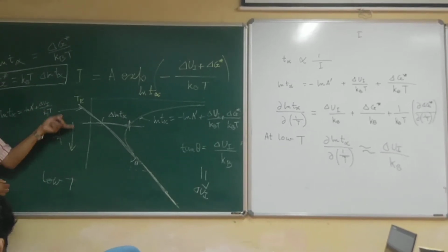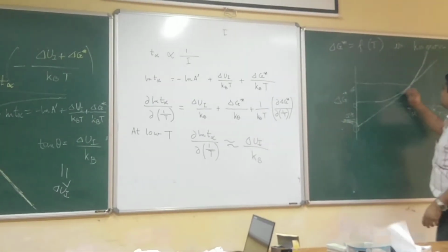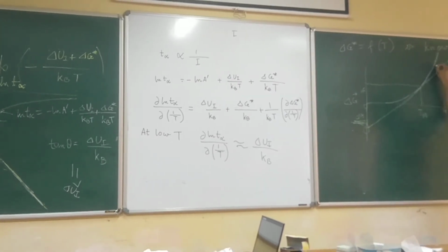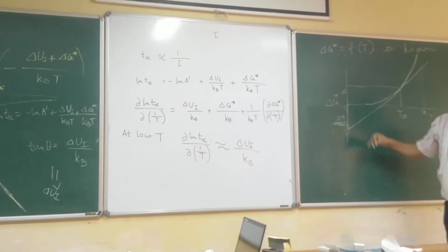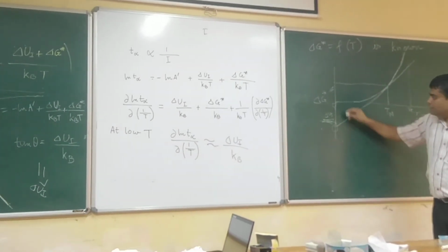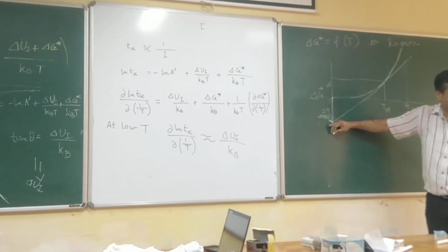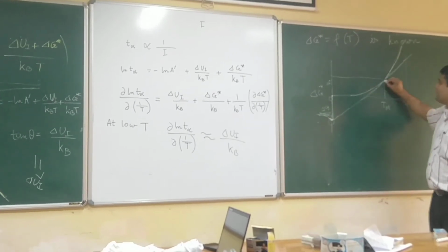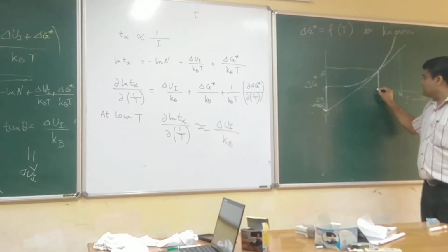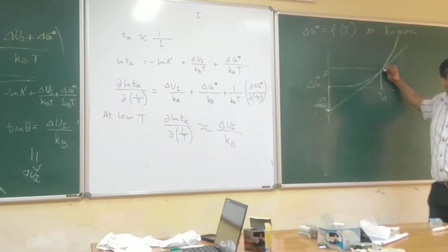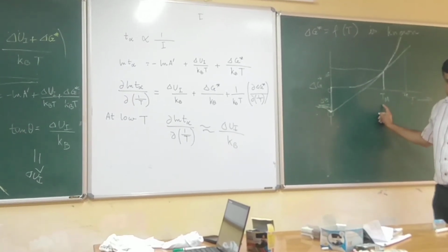So you repeat that over different temperatures. You will get how delta G star varies with temperature, this white curve. So from that you can get delta ui. Then from this, you first find out on this where delta ui is, from 0 towards negative. Then draw a tangent on this curve from that point. That particular point where it will intersect or just be tangent to that curve will be your temperature where nucleation rate is maximum.